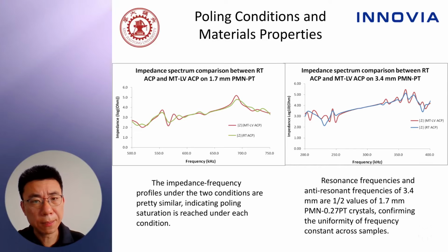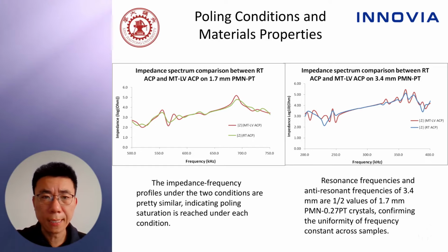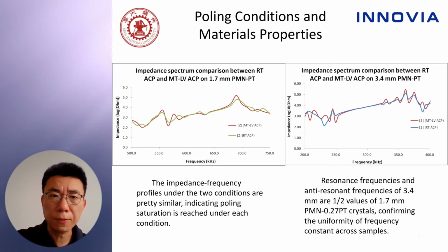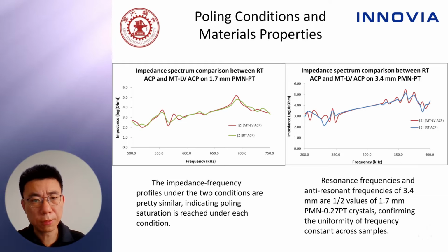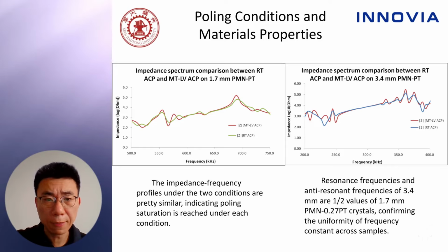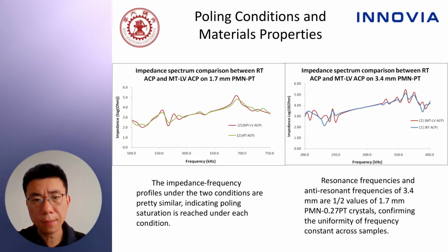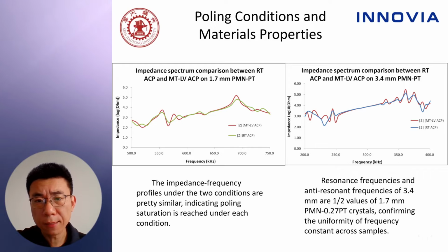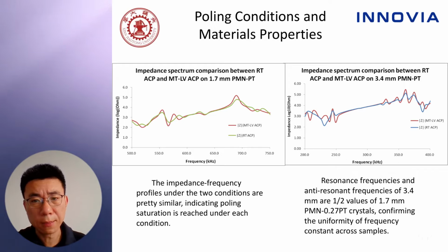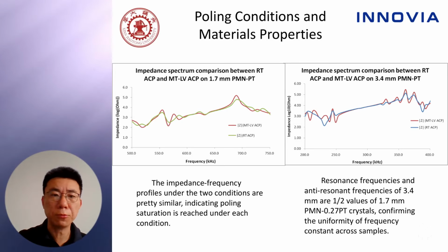Now, looking at the impedance spectrum comparison between RT-ACP and MT-LV-ACP on 1.7 millimeter PMN-PT crystals. The graph on the left shows that the impedance frequency profiles under 2 conditions are pretty similar, indicating poling saturation is reached under each condition. The graph on the right shows the resonance frequency and anti-resonance frequency of 3.4 millimeters are half the value of that in 1.7 millimeters, confirming the uniformity of frequency constant across different samples.